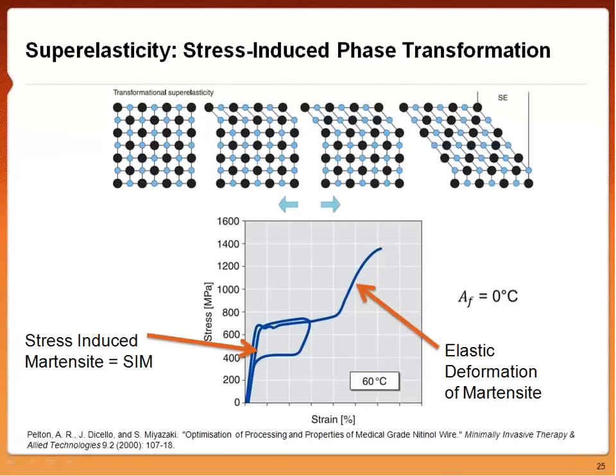And just to illustrate in the picture over here, this is a sample that was pulled at 60 degrees Celsius, and that has an Af finish of 0 degrees Celsius, meaning that at 0 degrees Celsius, a raw piece of material has 100% austenite, and then it's loaded in a tensile test.